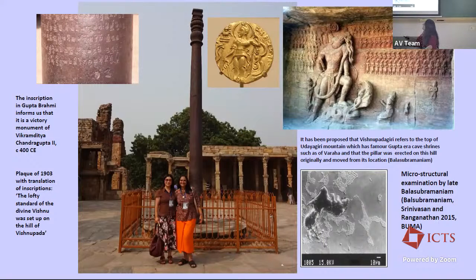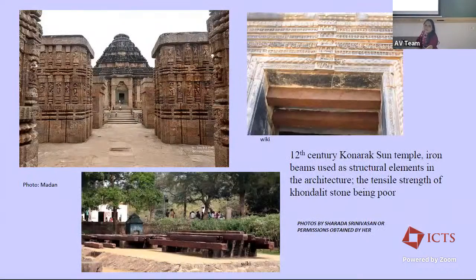And one of the interesting aspects about the Delhi iron pillar is the corrosion resistance. Some scholars had analyzed it earlier, and even Hadfield had analyzed the Delhi iron pillar, and they found significant traces of phosphorus, about 0.2% or so, which could have contributed to the corrosion resistance of the pillar. And of course, the Delhi iron pillar is more a ceremonial pillar, so it doesn't have any real functional use. But interestingly, there was the use of iron for functional purposes, for the tensile strength of wrought iron, in the Konarak temple. There were at least about 200 wrought iron beams used in Konarak. And of course, the stone that is used in Konarak itself has very poor tensile strength.